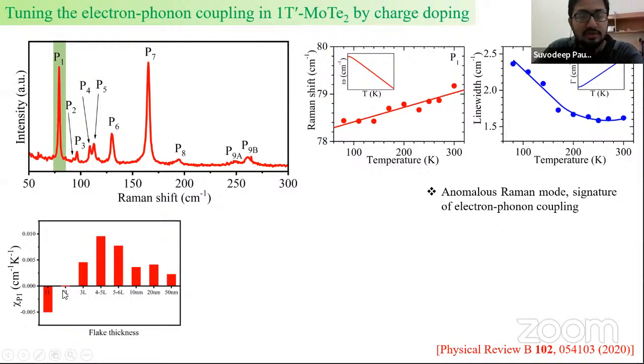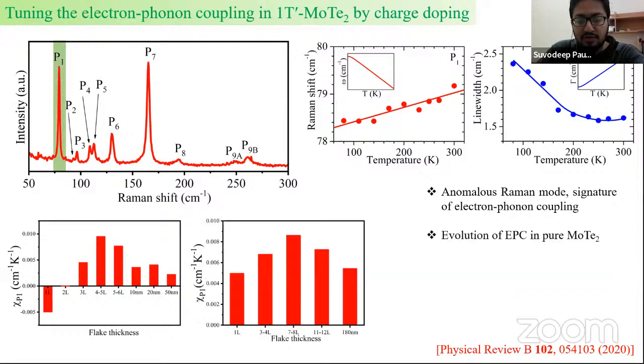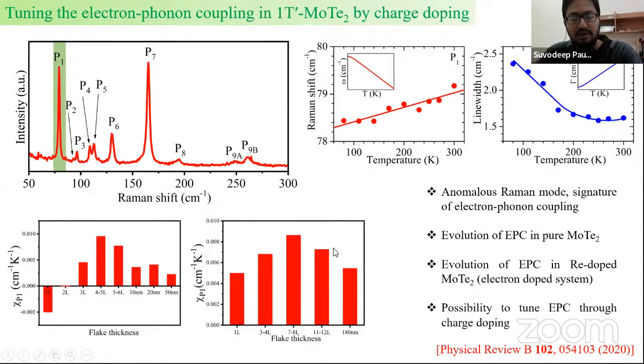This is also consistent with the fact that the very thin layers of TMDs get very strongly hole doped when they are exposed to atmospheric air and moisture, for example. However, in our study on the rhenium doped samples, which are rich in electrons, we see that the suppression of electron-phonon coupling is not strong enough. And from these observations, we could infer that electron-phonon coupling strength in this system could be tuned by charge doping.